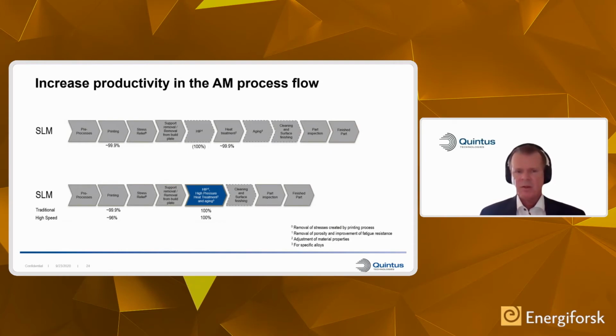You can also elaborate a little bit with printing speeds, so you don't necessarily have to print to a very high density. You can perhaps print a little bit faster, which will result in a lower density before HIP, but after HIP you will have 100% density.